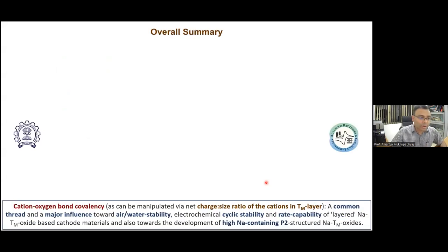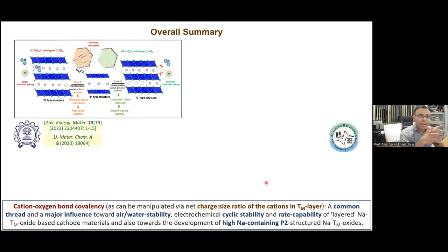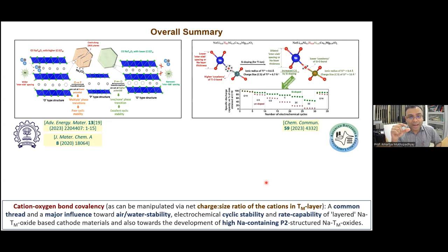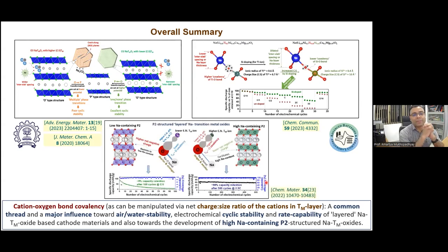So coming to the end of today's talk, let me summarize by saying that I hope I have convinced you today that by tuning the charge to size ratio in the transition metal slab, that is by tuning the covalency of the transition metal oxygen bond, one can suppress the instability of the layered sodium transition metal oxide in significant terms towards exposure in air and moisture. That is, make it stable even upon exposure to air and water, and possibly render it suitable for developing aqueous process cathodes. One can use the similar concept of covalency of the transition metal oxygen bond to enhance the rate capability of the layered transition metal oxide cathodes, and also develop high sodium containing P2 structured layered transition metal oxide cathodes.